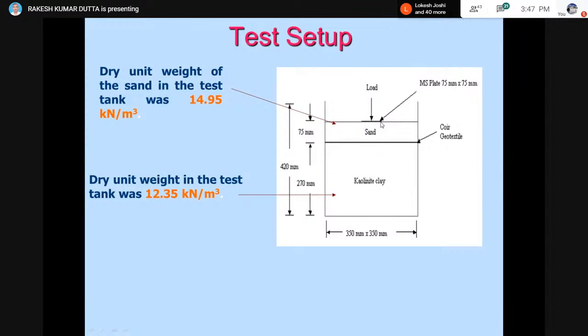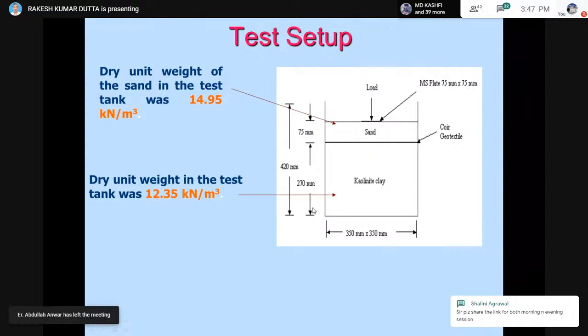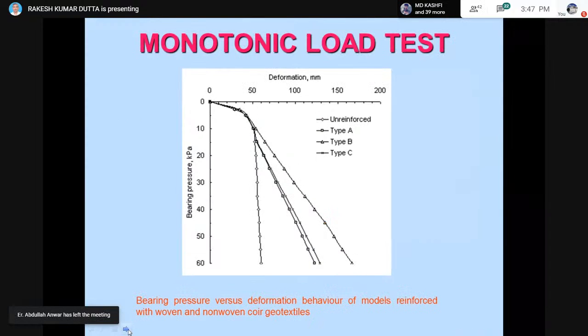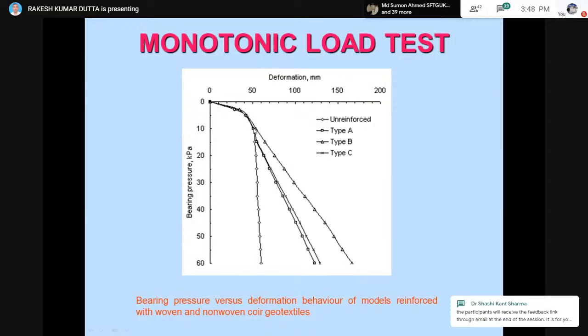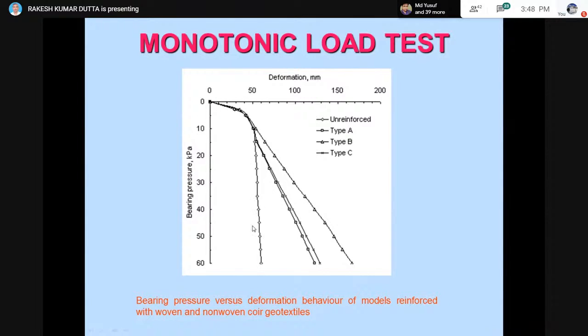The load was applied using a mild steel plate of 75 mm by 75 mm. Now if you see the curves, the load or bearing pressure versus deformation curve, here you see without reinforcement your curve is like this. It attains some value here, and then it goes parallel, which means there is no change in the bearing pressure. It is constant; it is a punching kind of failure which is occurring below the load.